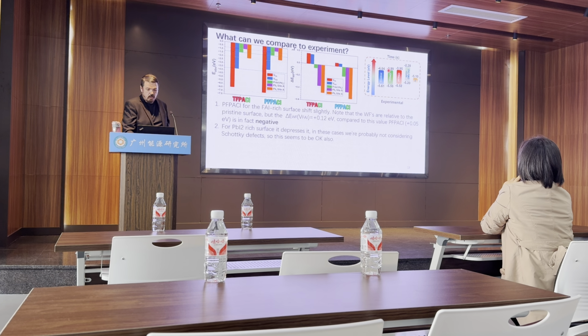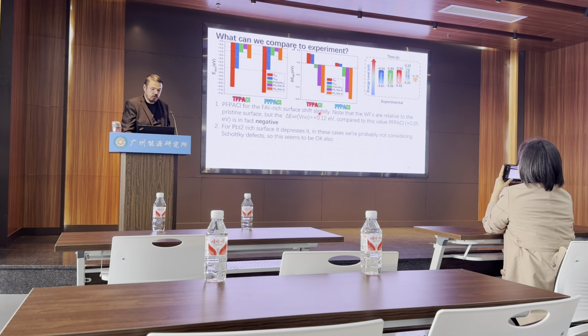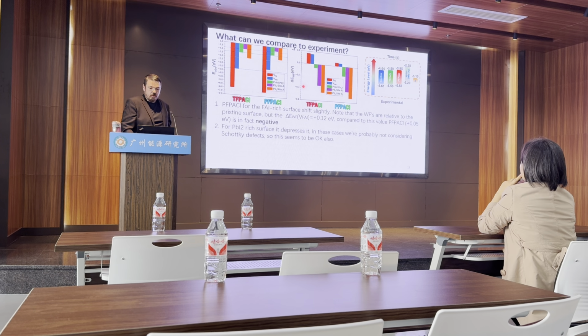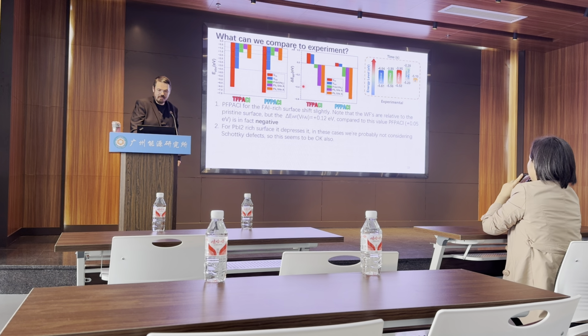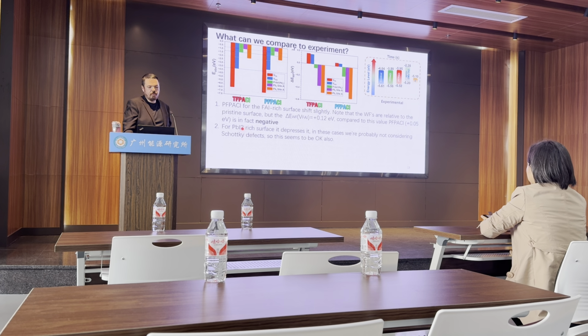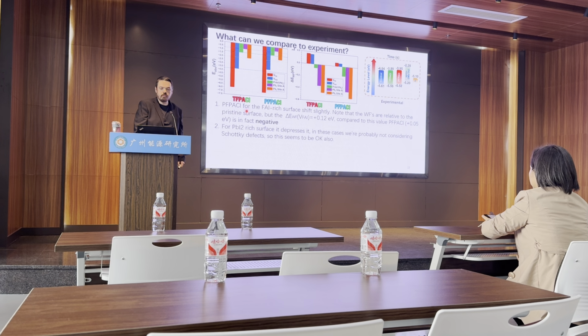So how do we explain this? Well, for the first case, which is probably more likely because this is the HTL perovskite case, we're actually passivating the Schottky defect. And the Schottky defect is actually plus 0.12 eV. So we compare here to pristine, we should be comparing to the Schottky. And when we do this, actually the shift is negative. So as we're healing the defect, our work function is going down. But when you compare it to pristine material, it looks like it's going up, so it's a complicated thing. In the PbI2 case, we're not really concerned about Schottky defects so much, so the fact that it shifts it down seems okay also.